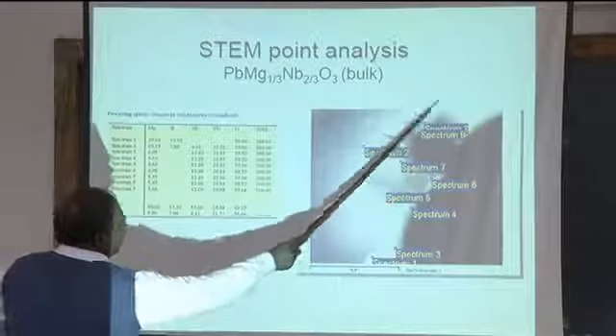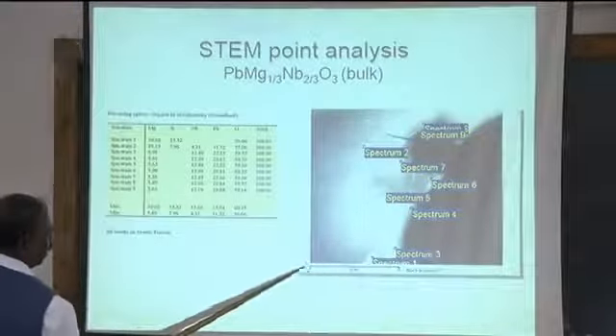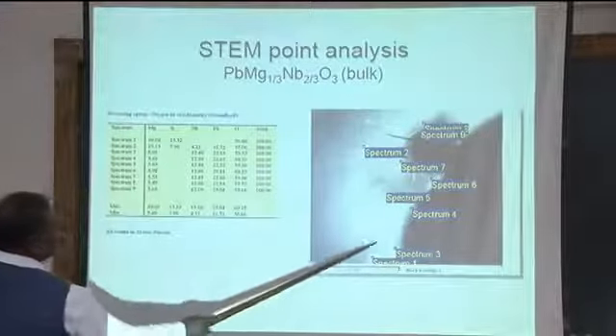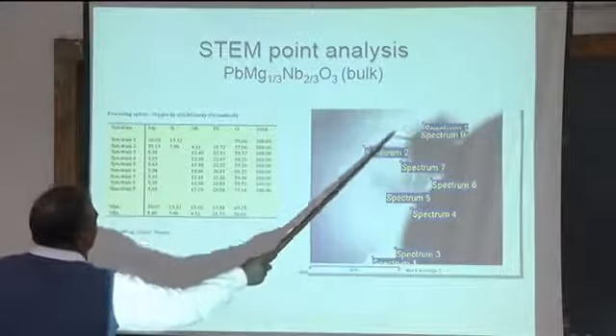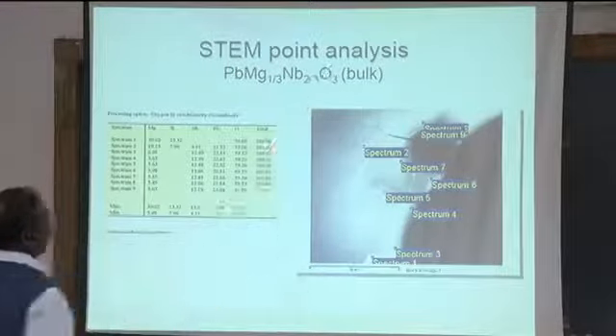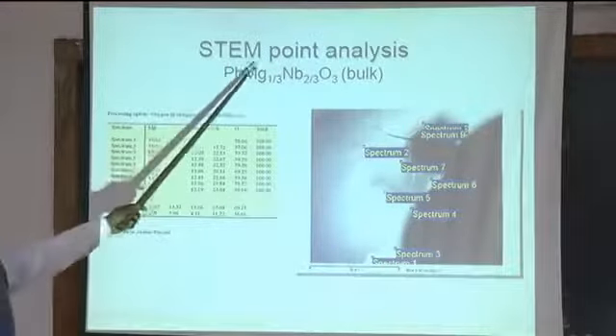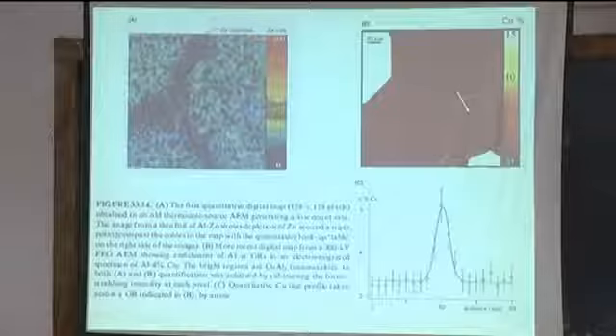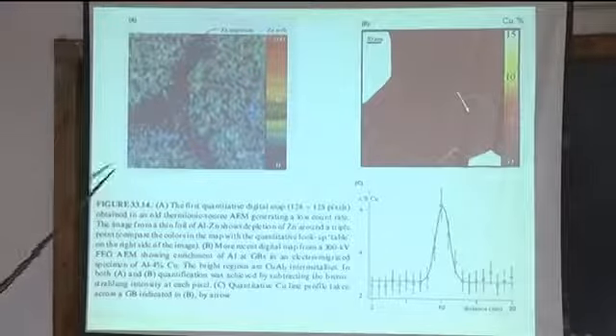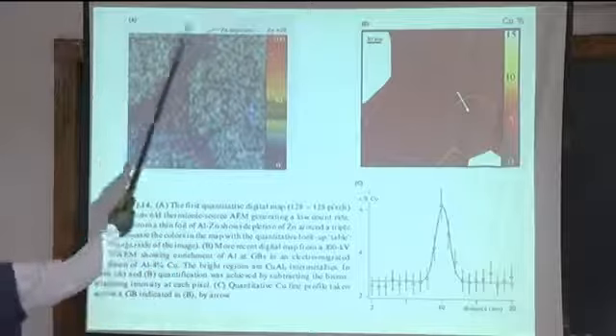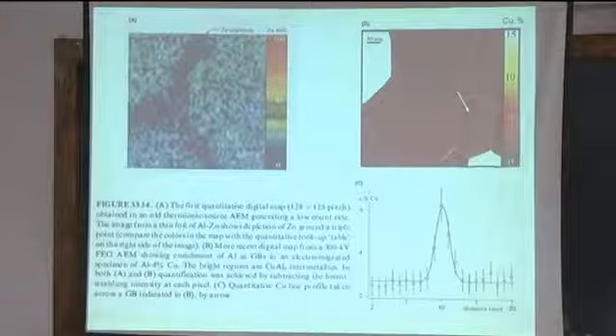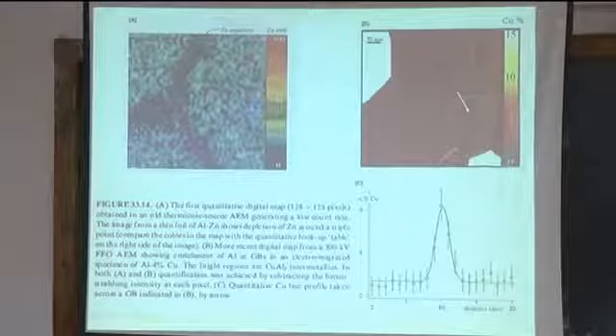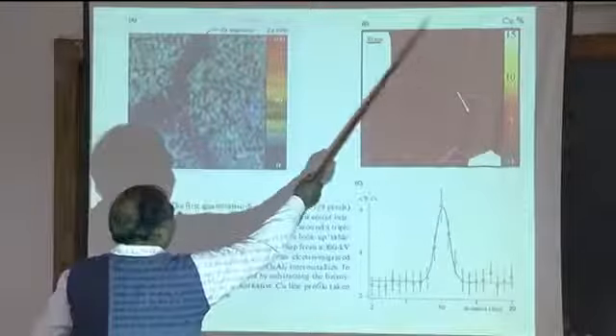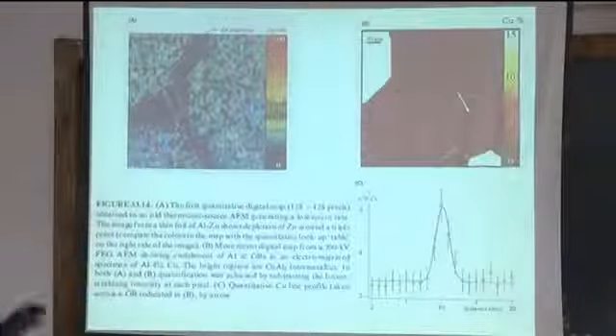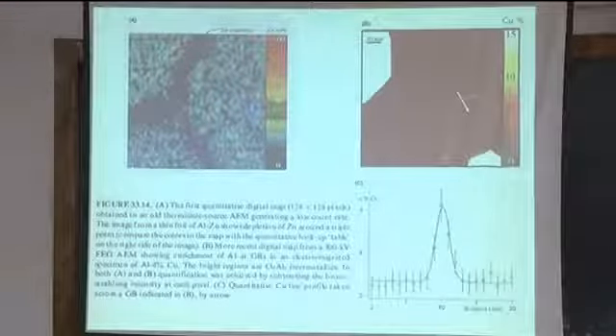You can obtain spectra from various regions. This is a TEM image. This is a marker to show the size. You can obtain it at a grain boundary, and whatever phase is required, you can get analysis. This is a scanning transmission electron microscope point analysis. This is the sort of mapping one used to obtain about 15 to 20 years back. Very poor quality. But latest, this is the level of mapping that has been achieved with EDS in a TEM.